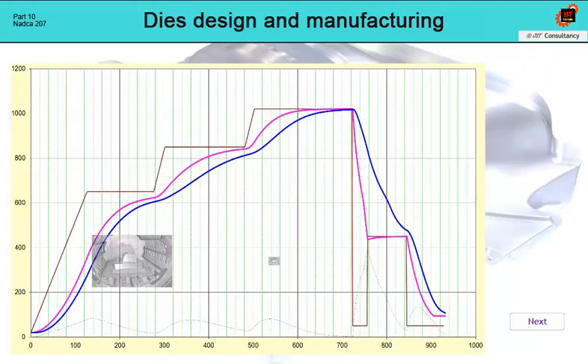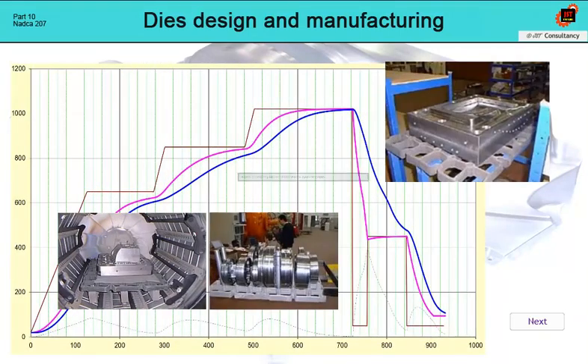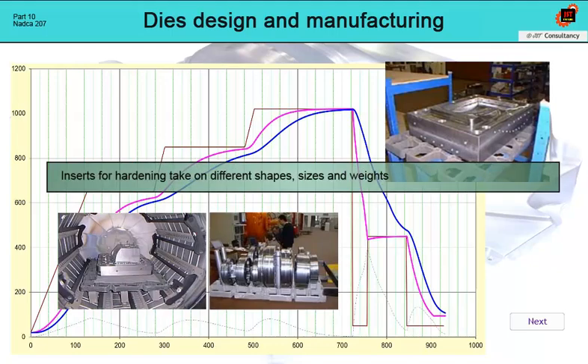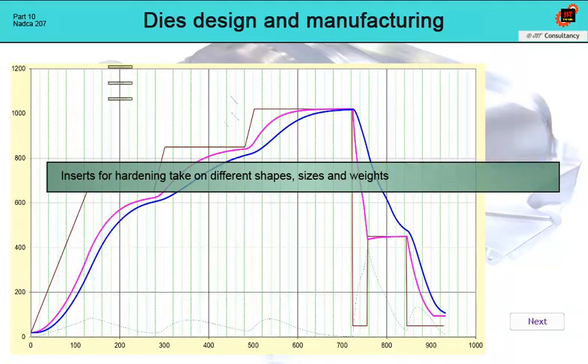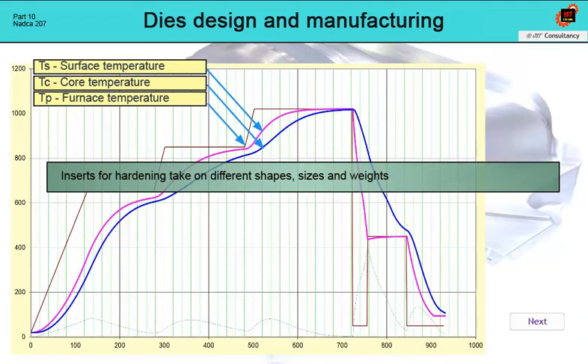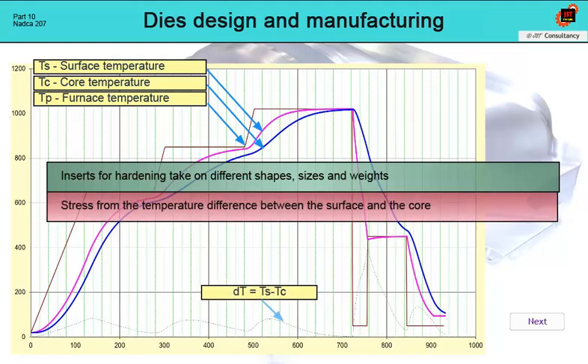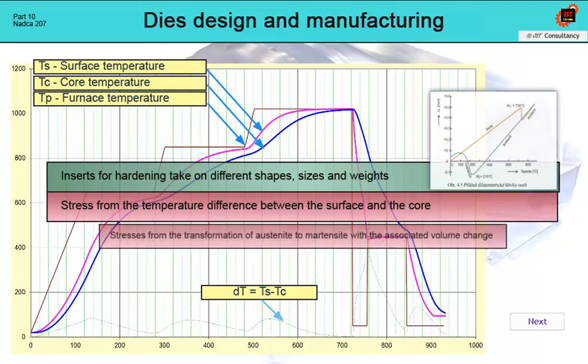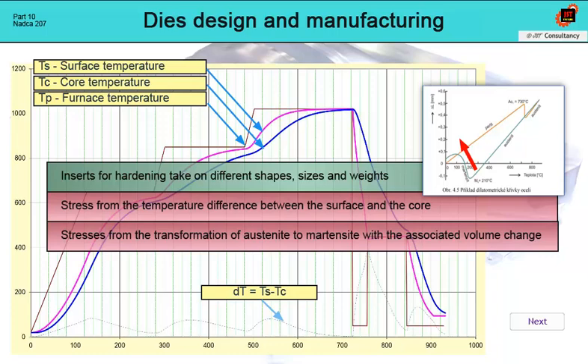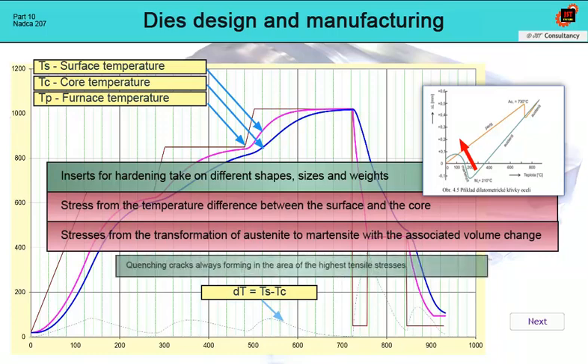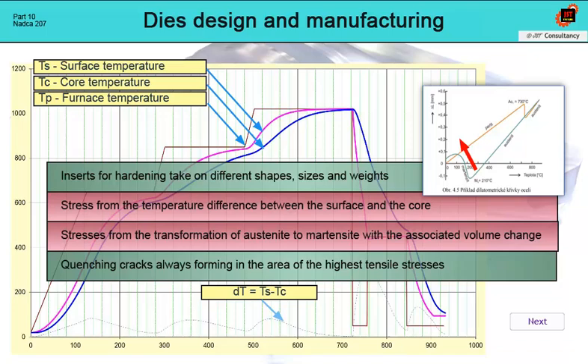As previously stated, die-casting dies come in a variety of sizes, shapes, and weights. Regardless of this uniqueness, it is necessary in all cases to ensure high-speed quenching, guaranteeing the correct structure, with maximum impact strength. During the heat treatment process, the parts are subjected to stresses, both tensile and compressive, which originate from the temperature difference between the surface and the core of the part, and from the transformation of austenite into martensite during hardening. Hardening cracks then appear in areas where the maximum tensile stresses are located. We will show which areas they are next.